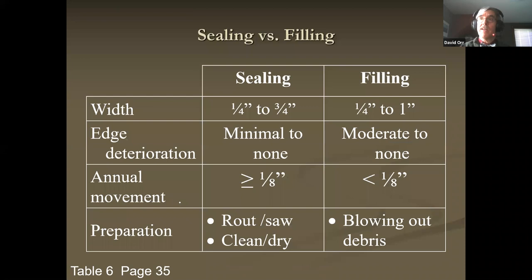Okay, this question about what kind of crack. What you want to do is look at the width of the crack. The cracks need to be wide enough to actually get a pin or a pencil into them. Okay, so at least a quarter of an inch. But if it's more than about 3/4 of an inch, it's going to be really hard to get the sealing materials into it. If it's more than an inch wide, there's no point in filling it. You're not going to get much reinforcement. You're going to have to look at either doing a patch. You could use some of the new modern mastics that have polymers in them. But again, you're not crack repairing at that point. You're doing more of an area kind of repair.